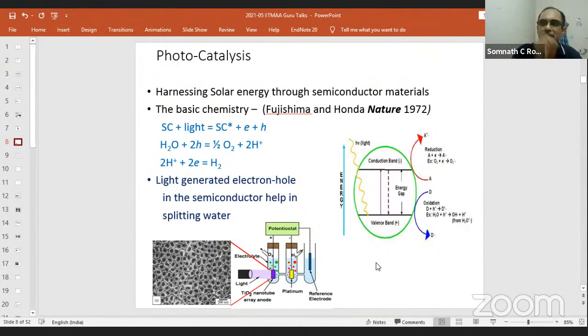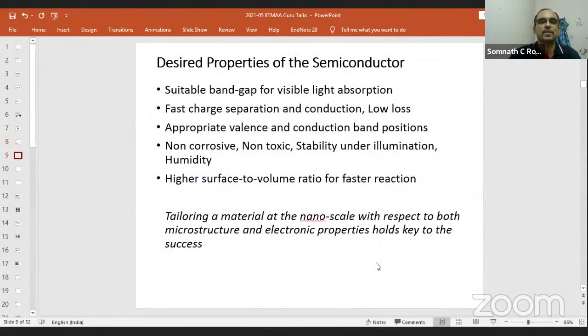So our research is around this theme of developing a semiconducting material that will help in producing hydrogen from water using sunlight. Just some technical stuff here: if you want to use sunlight, obviously you want the major portion of the solar spectra to be absorbed. Sunlight has about 4 to 5% UV, about 45% visible, and then IR. In principle, you want your material to absorb the entire sunlight.